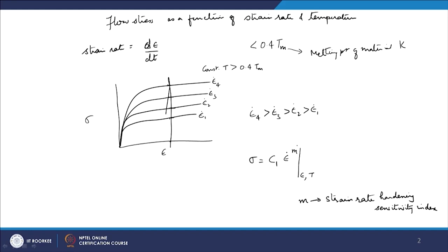So, this m is defining the strain rate sensitivity index of the stress, or you can also call it strain rate hardening. It is similar to what we saw in the previous lecture where we talked about strain hardening. At low temperature, material experiences strain hardening. You can see in these curves the strain hardening part is very small, and in fact after a certain strain there is no effect of strain on the stress. So, there is no strain hardening at all. At higher temperature deformation, the strain hardening of the material is very low.